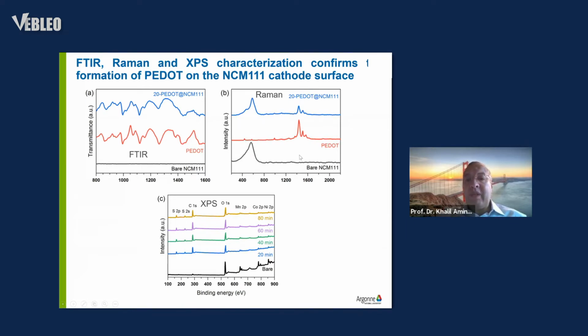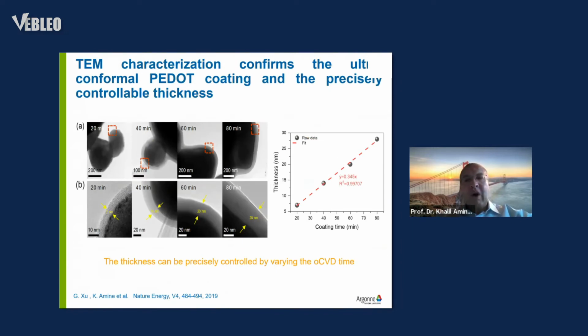We also compare the Raman signature of the PEDOT versus the coated material. You can see they are the same, and the same with the FTIR. So three techniques prove without doubt that we have a coating at the surface of the material. Next, we want to optimize the thickness of the coating, and we find out that the thickness is proportional to the coating time.